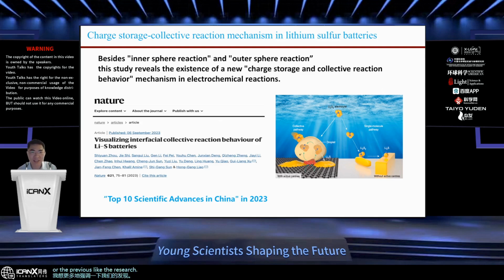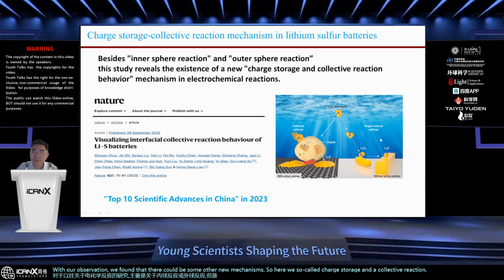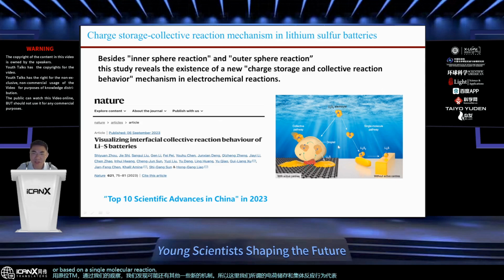For the previous research about electrochemical reactions, many were about the inner sphere reaction or outer sphere reaction, but with the in situ TEM, with our observation, we found that there could be some other new mechanisms. So here we have the so-called charge storage and collective reaction behavior. Previous work was all based on single molecular reactions, but once we found that there are a lot of molecules on the surface that aggregate together, they could be united and connect to each other. Their reaction pathway could be totally different, and this could also imply that the previous simple electric double layer model, in some cases, may not be totally right. There could be other situations that exist.